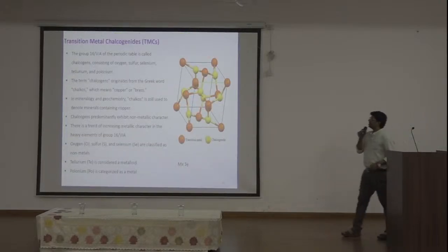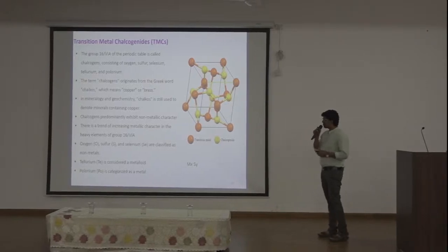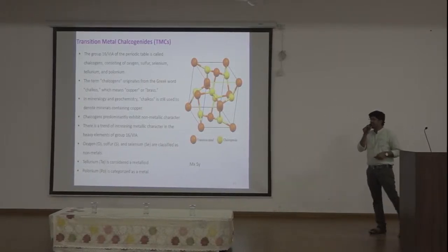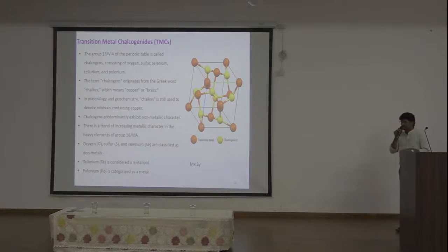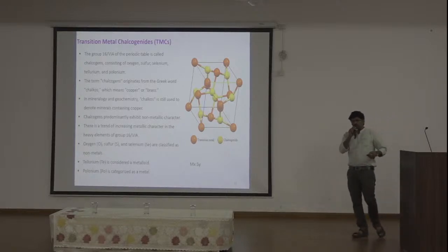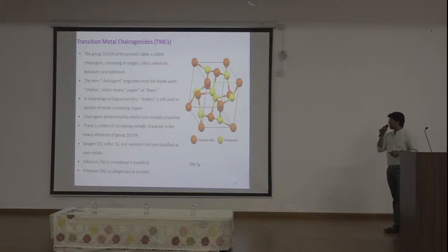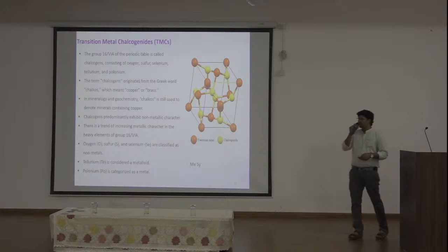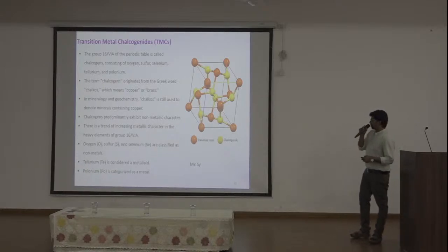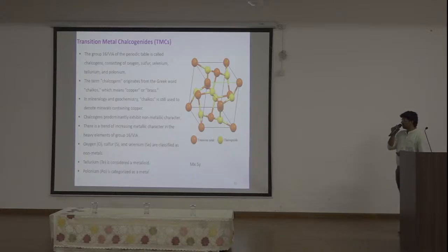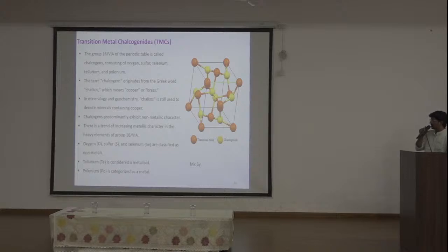Apart from this, the transition metal chalcogenide has highly electrocatalytic activity. A transition metal like nickel, cobalt, or molybdenum is combined with a chalcogenide like oxygen, sulfur, or selenium to improve the electrocatalytic activity. And when we tune the chalcogenide concentration, we can achieve higher electrocatalytic activity, which also improves the overall performance of the dye-sensitized solar cell.